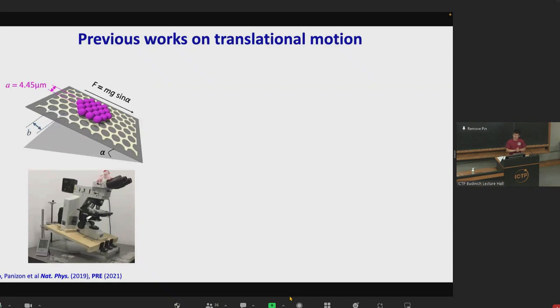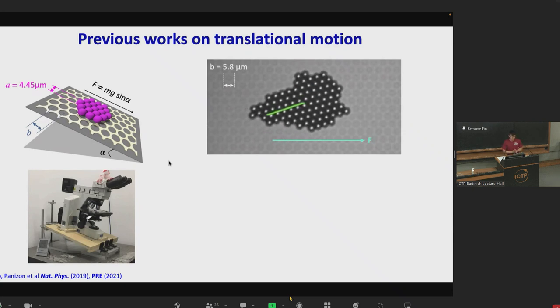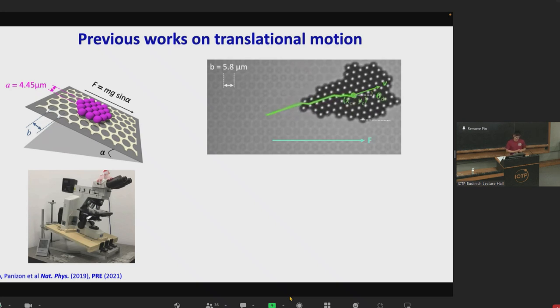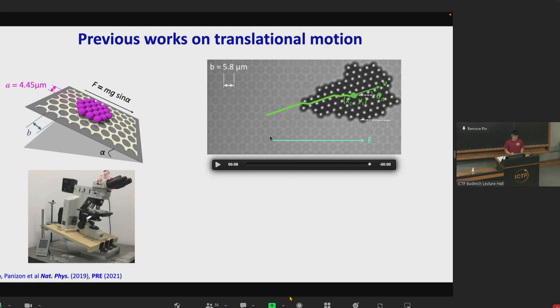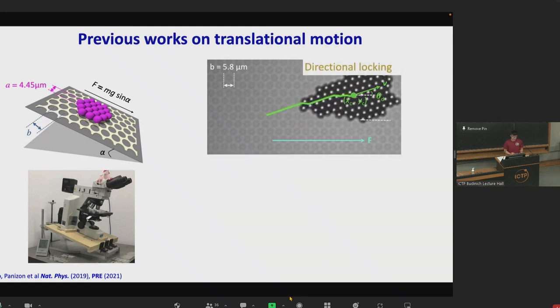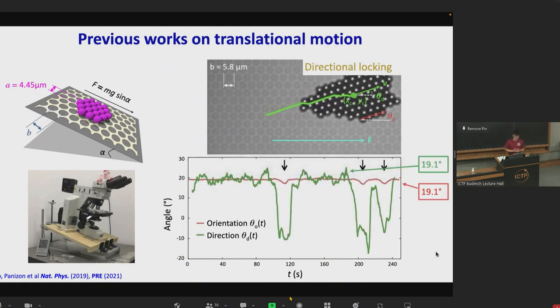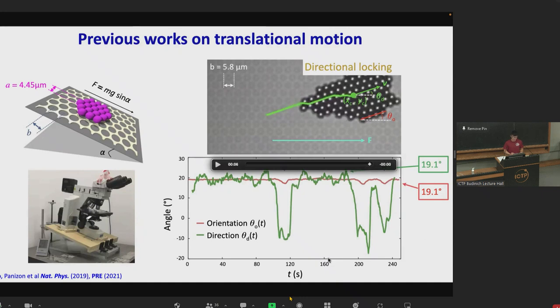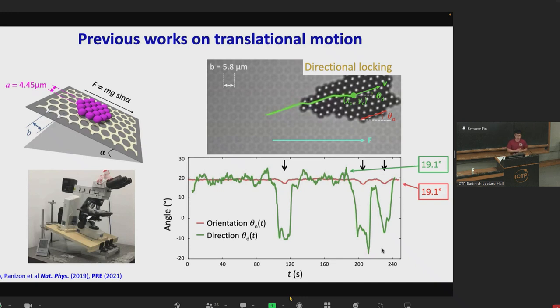Before showing the results of rotational friction, I would like to present some previous results first. In the previous works, I applied a constant force to a colloidal crystal and let the crystal slide across periodic surfaces. This movie shows the sliding motion of the colloidal crystal across the periodic surface. The force is applied in the horizontal direction and we see that the direction of motion of the crystal is in a different direction — this is called directional locking. We plotted the orientation theta_O and the direction of motion theta_D as a function of time, and we see that both angles are locked to 19.1 degrees for most of the time.